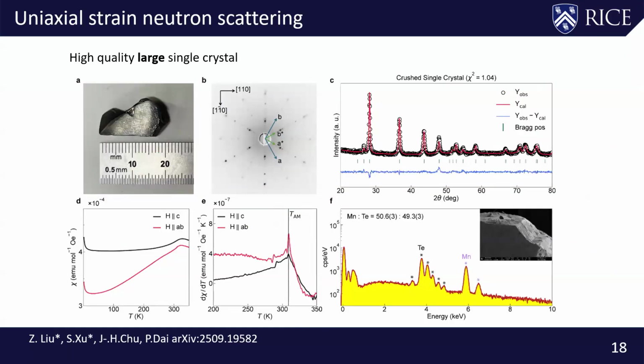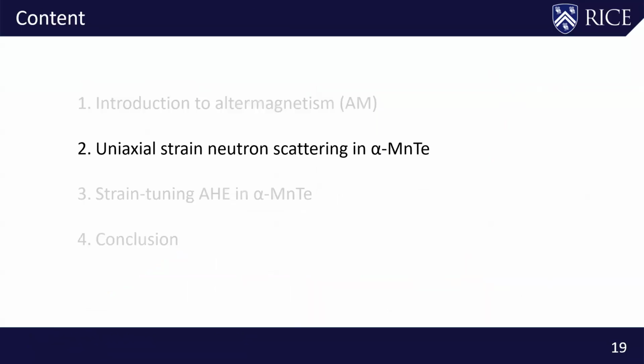So this is where our group came in. Shijie initially grew these samples that are very good and have the same Néel temperature as before, and then our transport measurement and chemical analysis show really a standard manganese telluride.